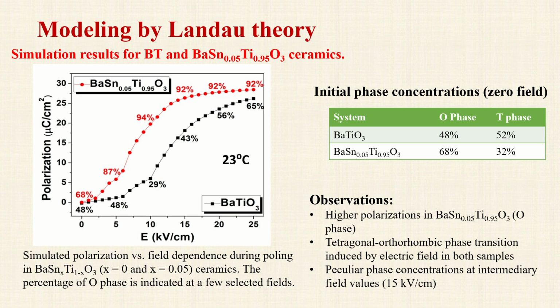For example, the minimum amount of the orthorhombic phase in undoped barium titanate is obtained for 10 kilovolts per centimeter, that is 29%, while the highest concentration in doped barium titanate, 94% of orthorhombic phase, is obtained at 12 kilovolts per centimeter.